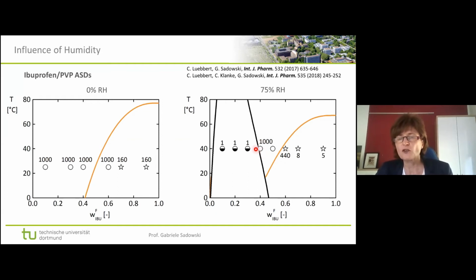which is a nice agreement with our prediction. Of course, we have a look at this sample. We will see whether it will for sure not demix anymore, and it will also not crystallize anymore. And that's why we believe that this, as well as this one, is stable. So that was very surprising for a pharmacist, because their experience usually is the higher the API content, the higher is the risk that something unwanted happens. But this time, it is really the ones in the middle.